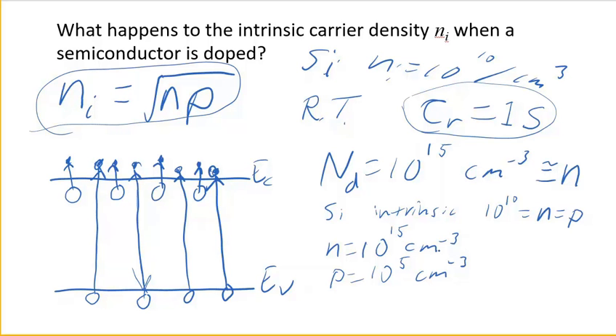And how do they get annihilated? By electrons going back home. So yeah, you lose electrons too, but losing 99,999 electrons out of 10 to the 15th is a total drop in the bucket. So you don't care. So the electron carrier concentration is really not affected by the thermal equilibrium condition. But maintaining the thermal equilibrium condition really drives down the hole concentration when you n-dope the semiconductor. And if you p-dope the semiconductor, it's the opposite case. So yes, those go down.